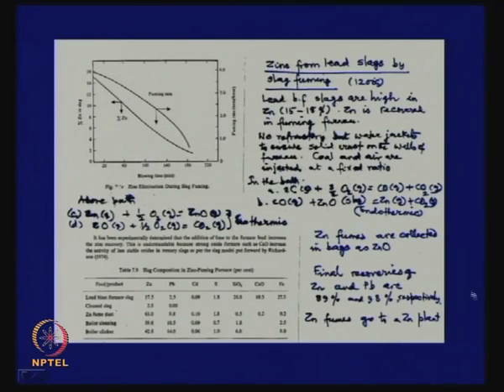Now, these zinc fumes and zinc oxide fumes are collected in bags. There are collection bags of zinc. If we can do that, we can recover nearly 90% of zinc from the slag, and then we will also improve recovery of lead to about 98%. These zinc fumes will go to the zinc plant. To get zinc out of that, it will go either for pyrometallurgical processing or for hydrometallurgical processing.